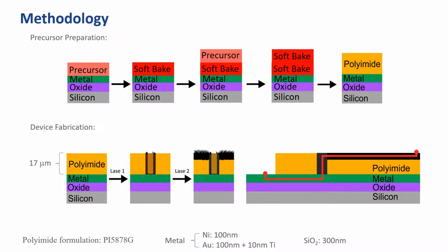For this initial demonstration, we followed traditional silicon fab processes to control the thickness of our polyimide film. The use of a wafer is not fundamental to the process we demonstrate, but instead allowed us to control our polyimide thickness and formulation. Two subsequent layers of polyimide precursor were cast and cured to achieve a suitable layer thickness of 17 micron.